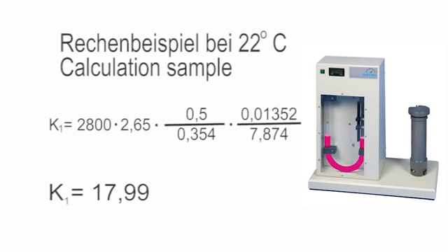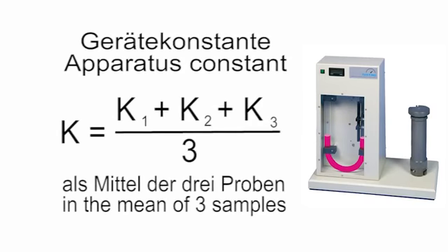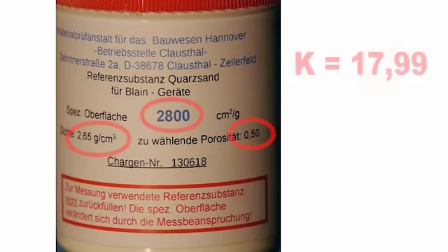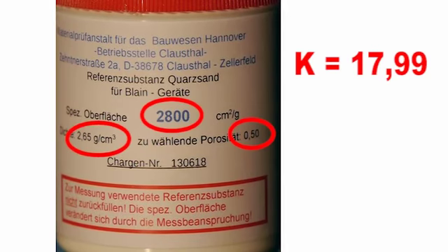A sample calculation. The apparatus constant of test 1 is determined from the mean value from 3 runs. A mean value is again calculated from the 3 apparatus constants from the 3 tests, which is then assigned to the tested comparator substance. In principle, the appropriate apparatus constants are determined for different grades of fineness.